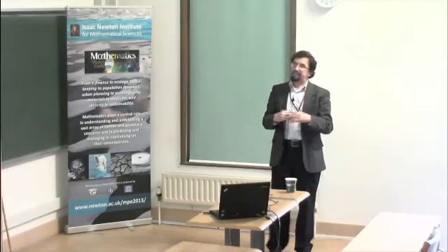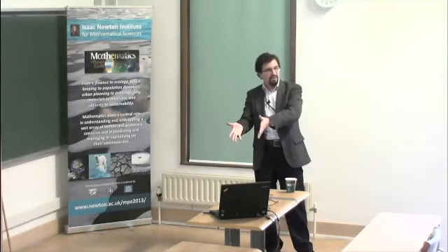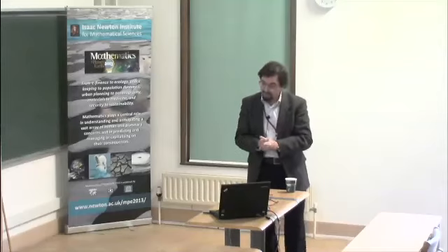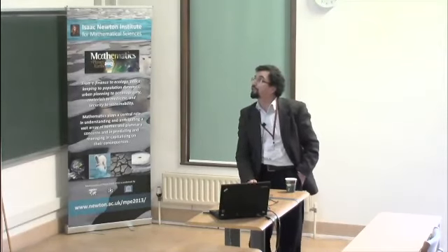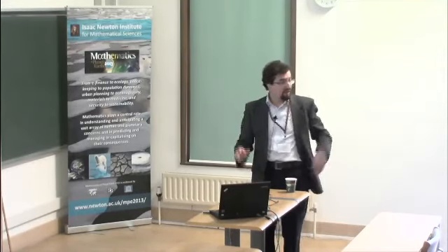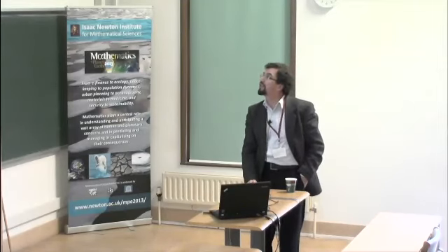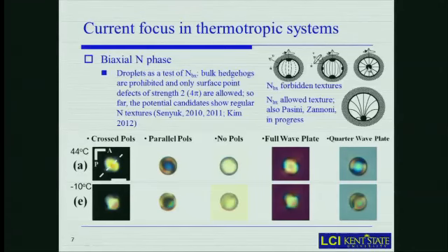And the symmetry of the phase dictates what types of defects you can produce in this phase. And if you consider the particular case of the spherical confinement, you would realize that you cannot, for example, have the point defect in the center, because if you have the radial director, then the second director will form spherical surfaces.